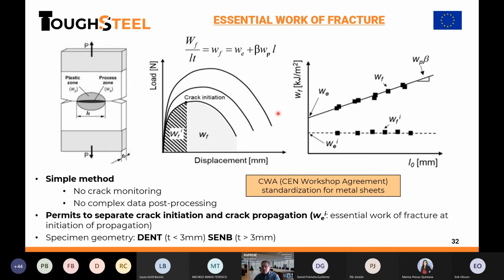What is interesting from this method as well is that if we detect by DIC methods or by optical methods the initiation of the propagation, we can also get the energy at the beginning of the crack initiation. And because this is just when the crack starts to grow, this is independent from the ligament. So the method is simple, no need for crack monitoring, only the load versus displacement curve. We can separate initiation and propagation.